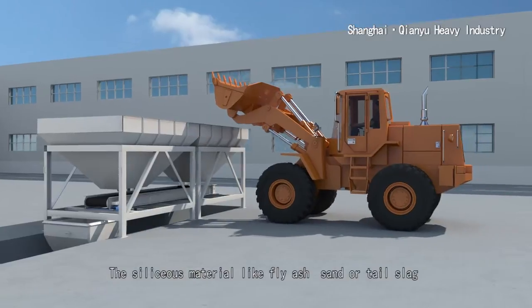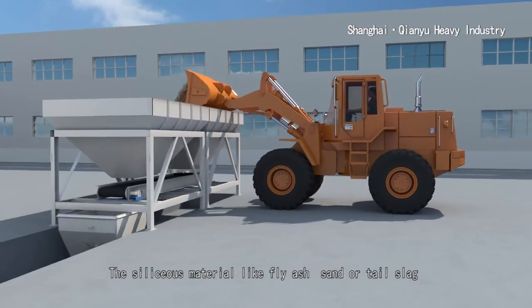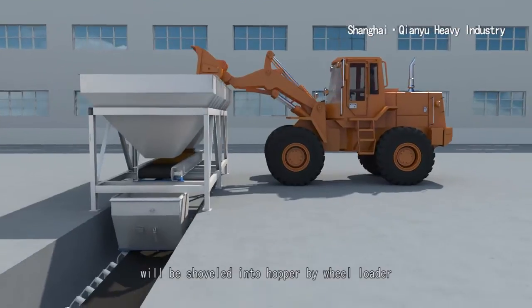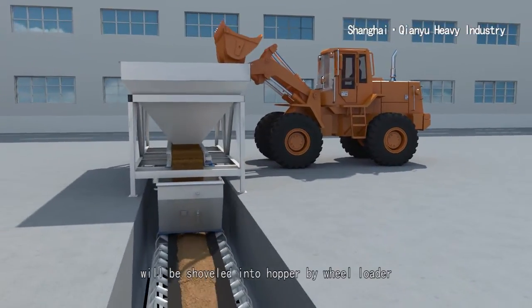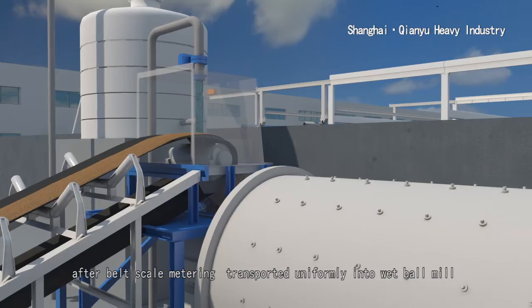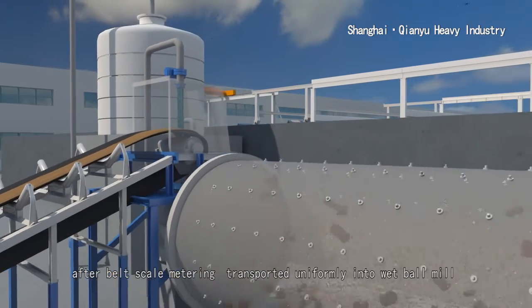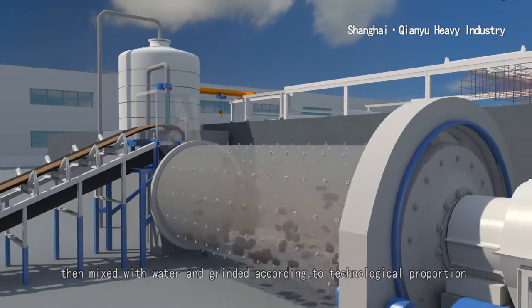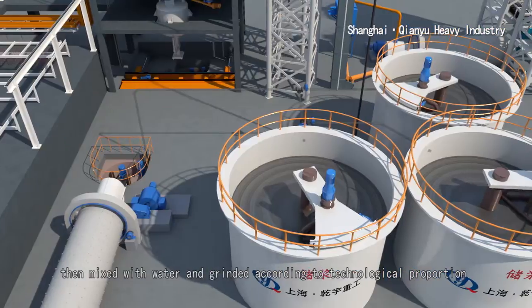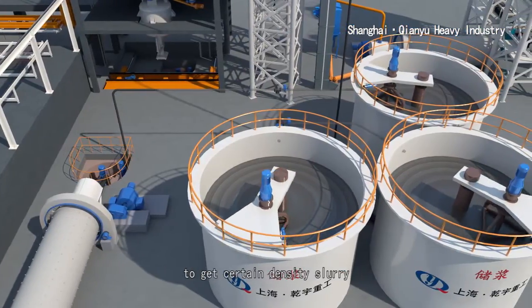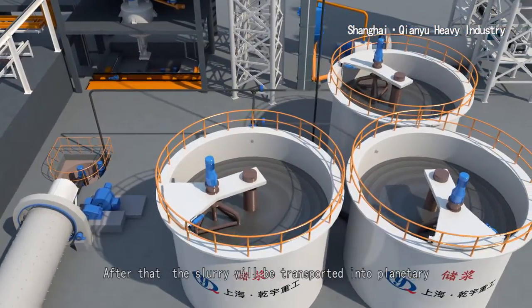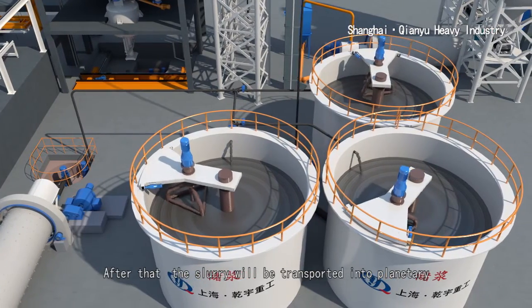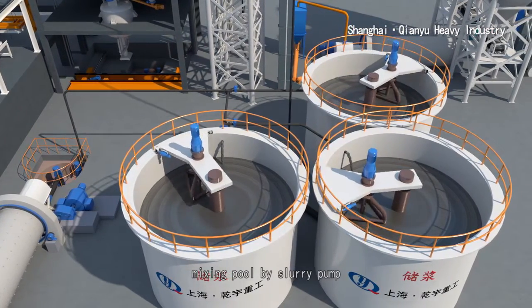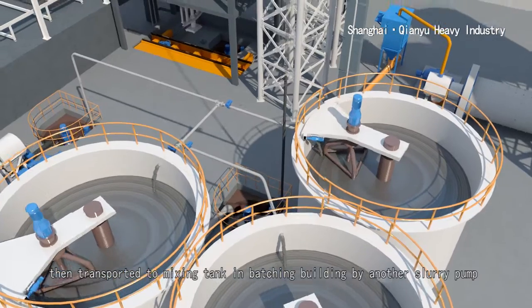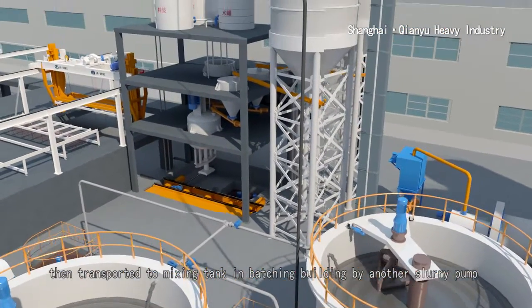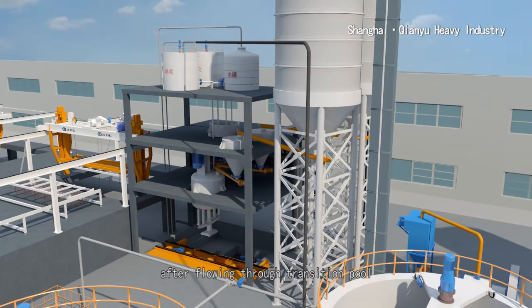The siliceous material like fly ash, sand, or tail slag will be shoveled into hopper by wheel loader after belt scale metering, transported uniformly into wet ball mill by belt conveyor, then mixed with water and grinded according to technological proportion to get certain density slurry. After that, the slurry will be transported into planetary mixing pool by slurry pump, then transported to mixing tank in batching building by another slurry pump after flowing through transition pool.